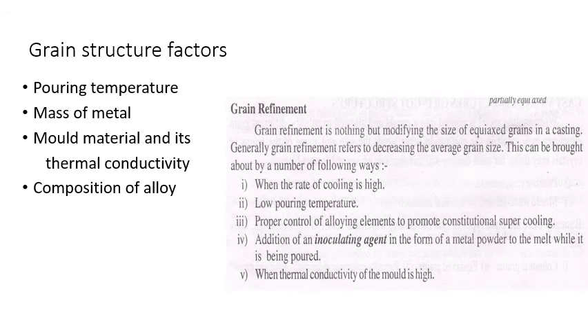Now how exactly can we control the type of grains we get in a casting? These things depend on the pouring temperature, the mass of the metal, the mold material and its thermal conductivity, and the composition of the alloy. All of these things are going to control the type of grains we get in a mold cavity. For grain refinement, the pouring temperature should be low, and it should freeze to room temperature suddenly. Then we are going to get a fine size.